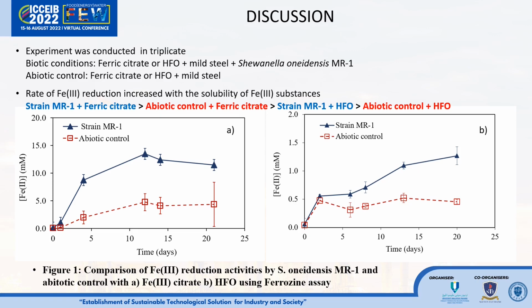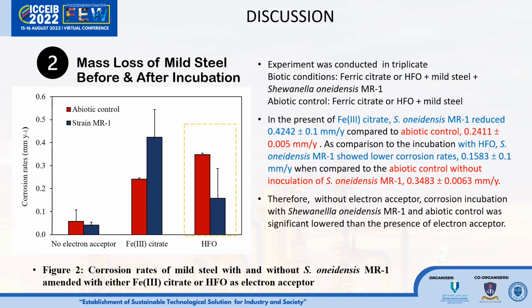We set up a similar experiment along different solubility of microbial corrosion experiment to evaluate steel mass loss before and after corrosion incubation. After 20 days of incubation, all corroded mild steels were taken out from the vials and evaluated for their mass loss. Based on figure 2, there was significant mass loss of steel treated with and without Shewanella oneidensis MR-1. In the presence of ferric citrate, Shewanella oneidensis MR-1 reduced 0.4242 mm per year compared to the abiotic control, which is 0.2411 mm per year.